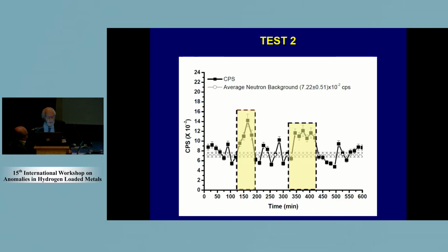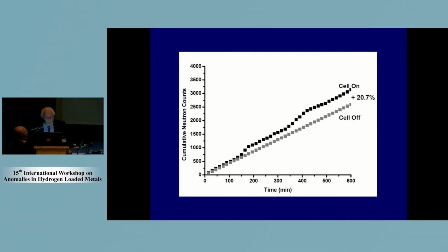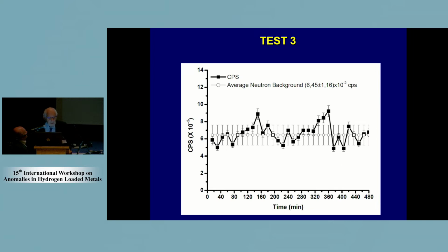The background in that period was measured very carefully. It was about 8, so higher than the previous one, and the peak is around 16 CPS, of course. Okay, and then in this case also we have a fork between cell off and cell on. It is around 20%. Then we had this test 3, where practically we have no peaks, unfortunately. We have some very small deviations with respect to the background, so we didn't conclude anything about test 3.